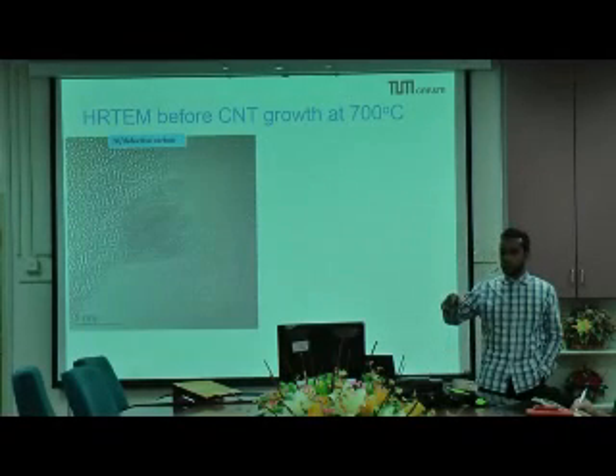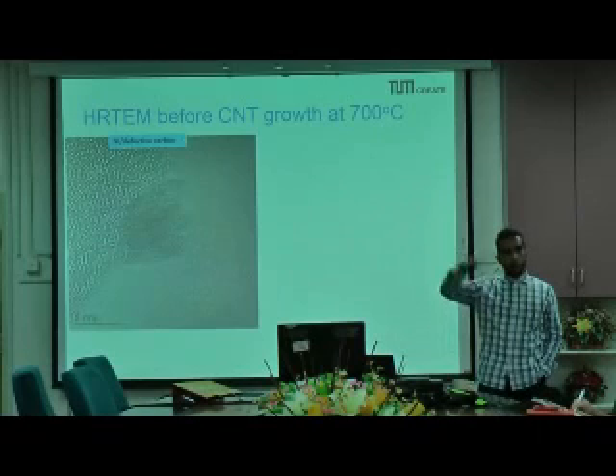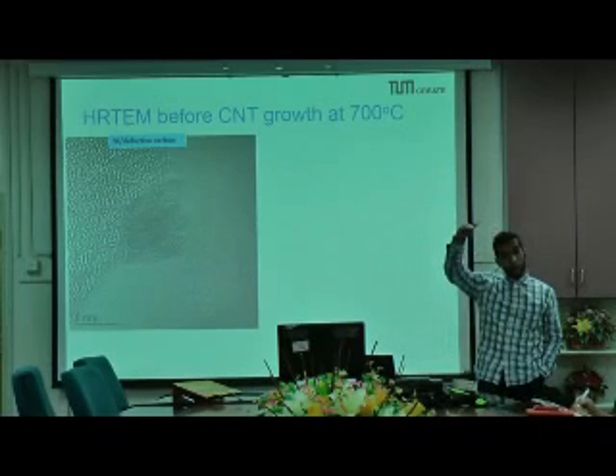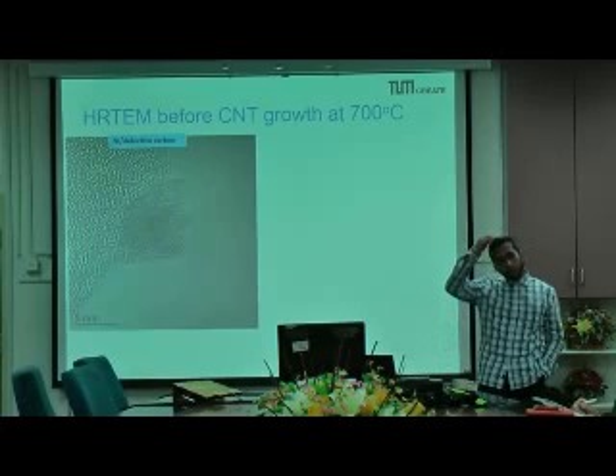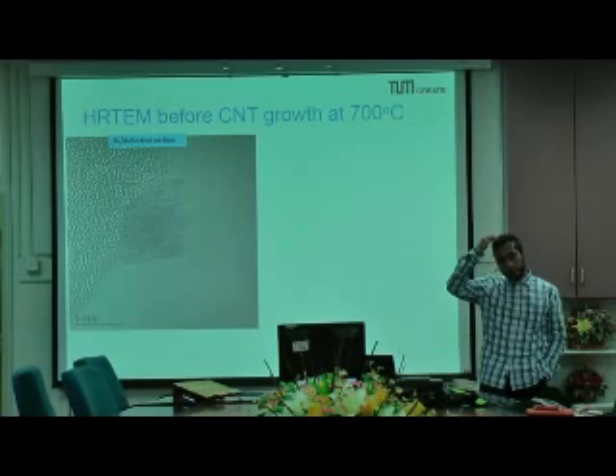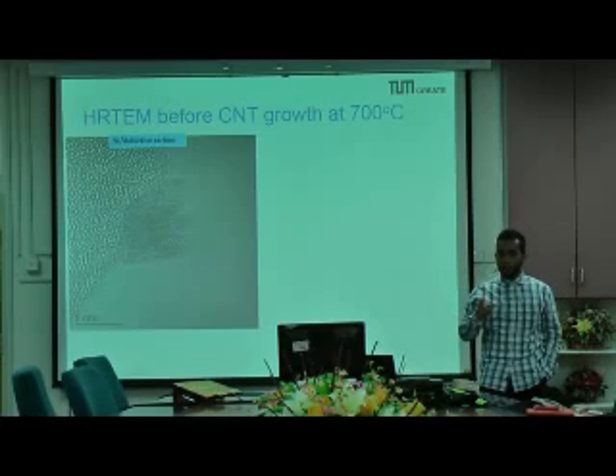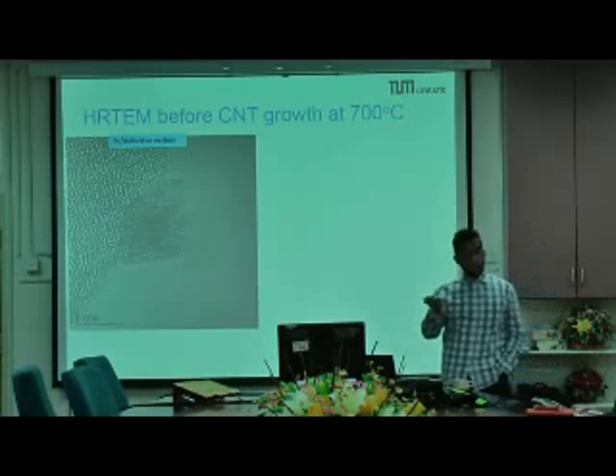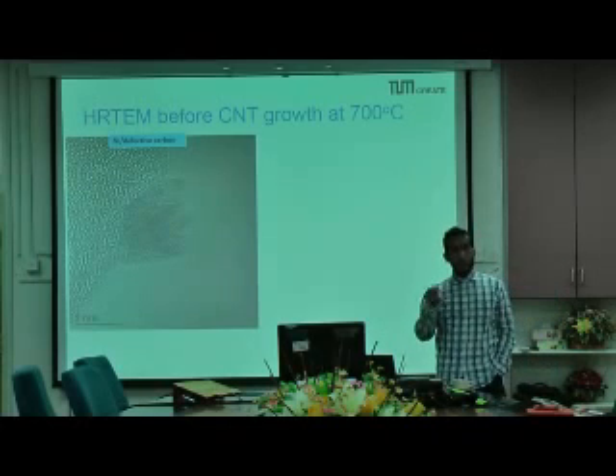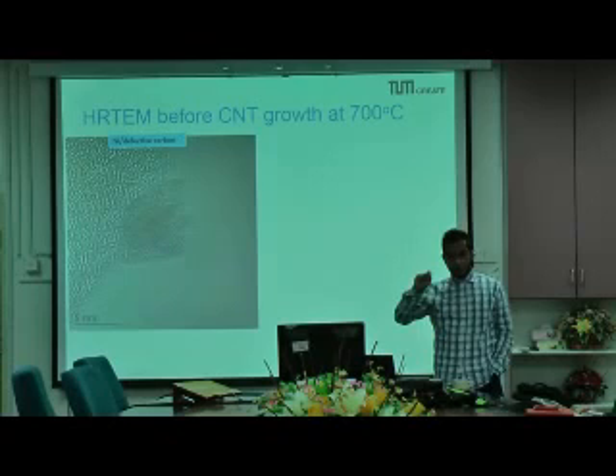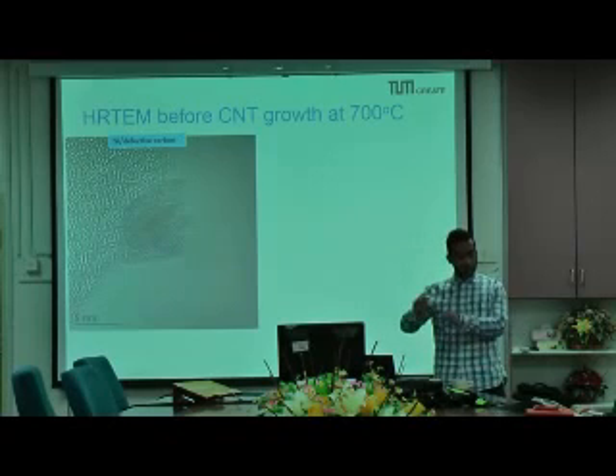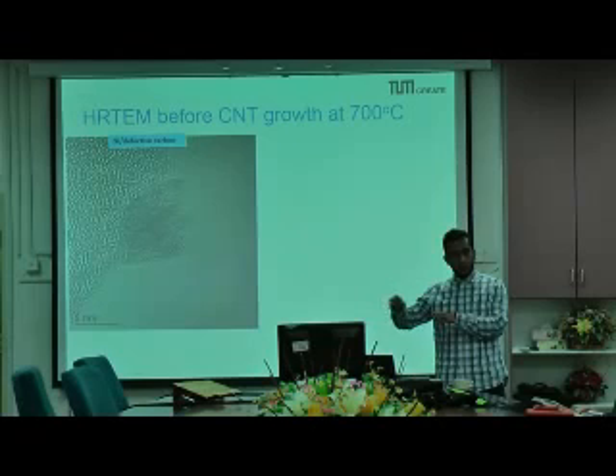When we did the TEM, this TEM is taken after the reduction. So you anneal, you increase the temperature to 700, and then you cool it down. At 700, if you do not have acid, you do not have the formation of the nickel. The nickel will have some carbon on the surface, but in my experimental conditions, the carbon is not high enough to allow precipitation during cooling. Although I've seen papers recently where they use significantly amorphous material, put nickel, increase the temperature in argon, and then you start to see deposition.